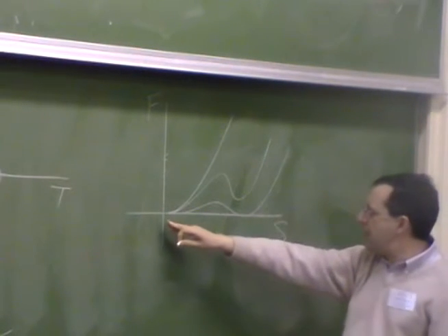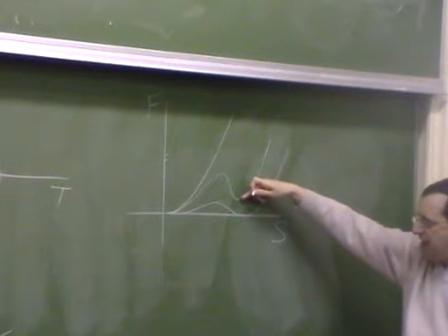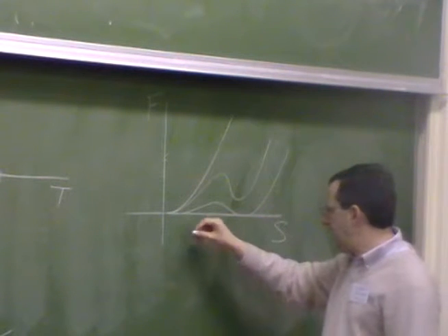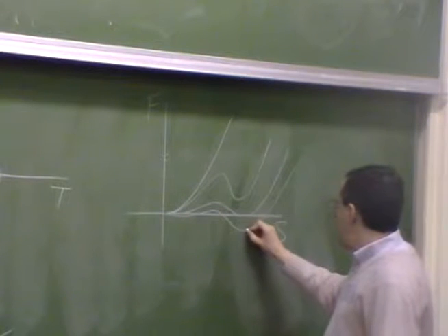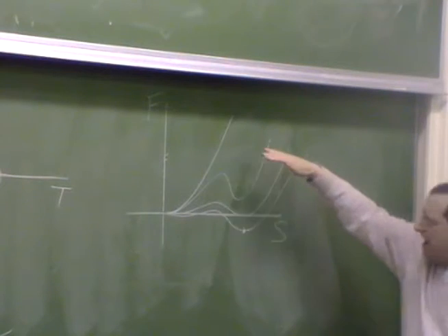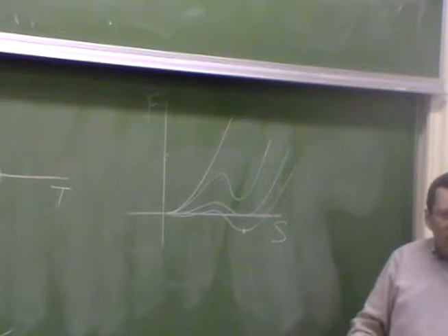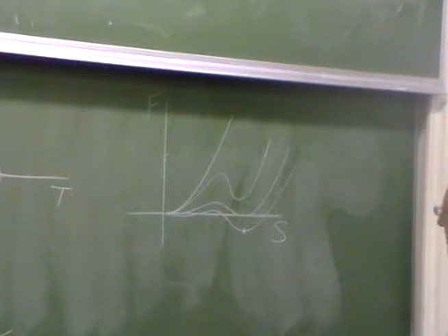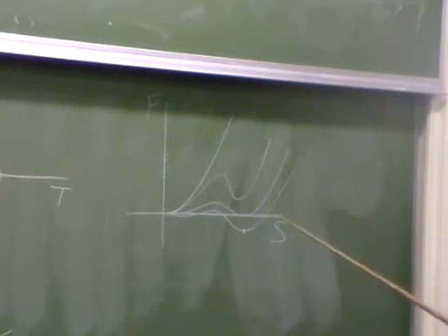And so here we would say there's an isotropic state, and it can have a metastable nematic state, or a first order transition from isotropic to nematic, and then at a lower temperature down to this kind of behavior where the nematic state becomes stable. Right? So this is the same kind of behavior that came from the big Maier-Saupe calculation that I showed you a couple of days ago. It gives the same kind of result, that there's a first order transition from isotropic to nematic.